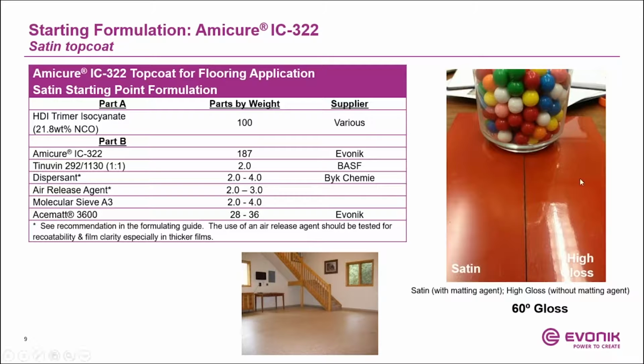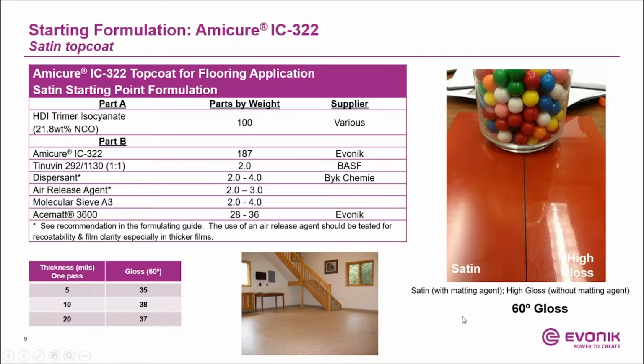Here's a picture on the right side. The panel here shows a high gloss finish, which is without any matting agent added. With the matting agent, you can get down to a satin finish. What we mean by satin finish is a 60-degree gloss of less than 40. This picture shows a real world application. A lot of times end users do not want a very high gloss finish because it shows all the small defects that you might see on the flooring. Going down to lower gloss, you're able to hide those defects better, and it gets a more pleasing look. I guess that's another reason.